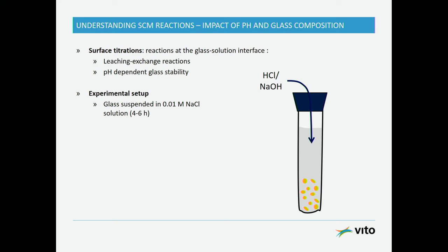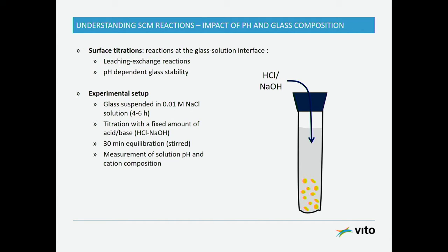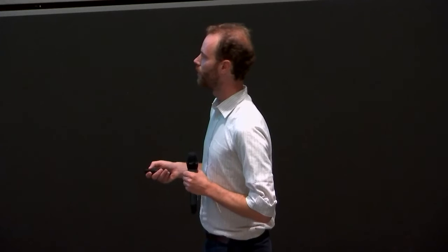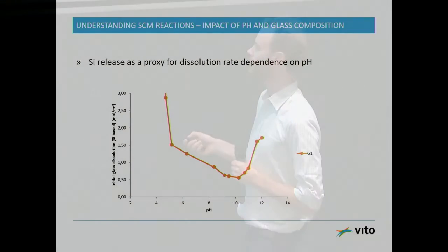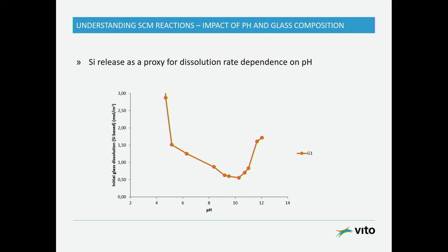We were shaking the solutions for some time, for 30 minutes, and then we were looking at what the outcoming solution pH was and what the composition was of the cations in the solution. Based on what comes out, you can actually calculate what the glass dissolution was during these first 30 minutes. This is for the most calcium-rich glass, and you see, okay, there is a clear dependence on pH. This is a very typical U-shaped behavior, so the higher the pH becomes on one end, you get more dissolution, and of course, when you go to very low pH, which you would never have in typical cement systems, then you get also much higher dissolution there.